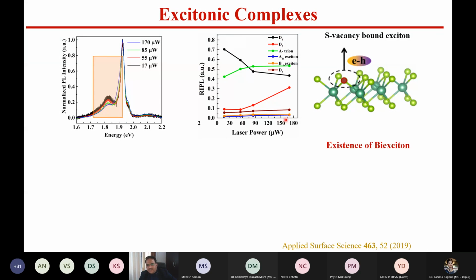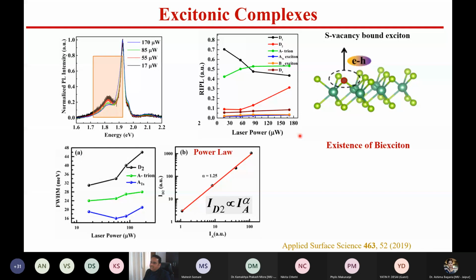We tried to understand that this is particularly coming from the sulfur vacancy bound exciton. A molybdenum vacancy can be there, but it is very rare to get the molybdenum vacancy rather than the sulfur vacancy. We also studied the PL peak FWHM versus the laser power, and we found there is a power law of the intensity of the D2 peak as a function of the intensity of the A trion.